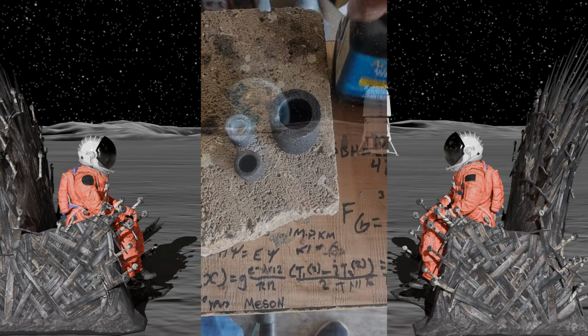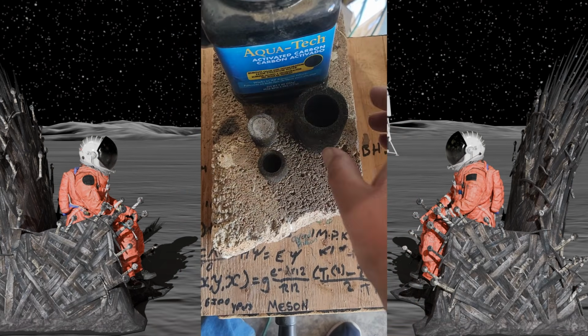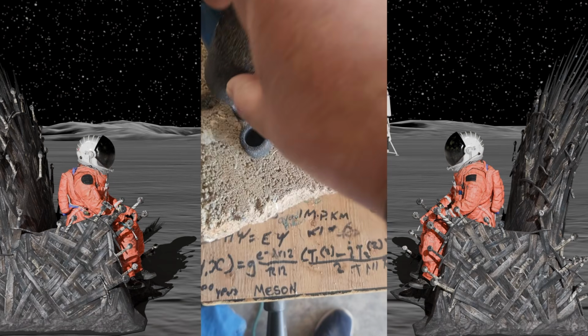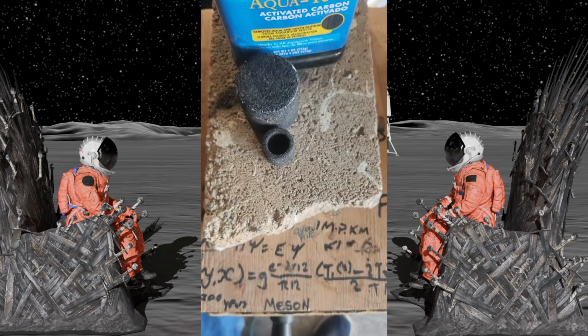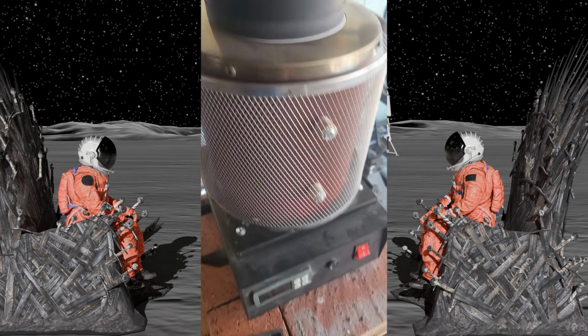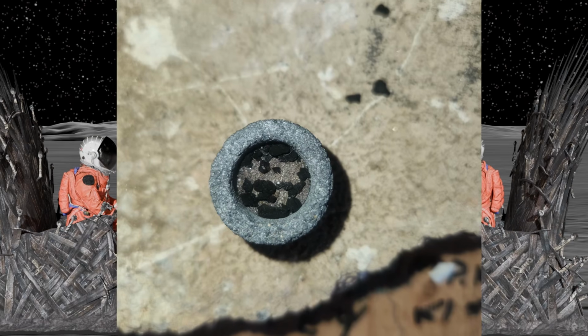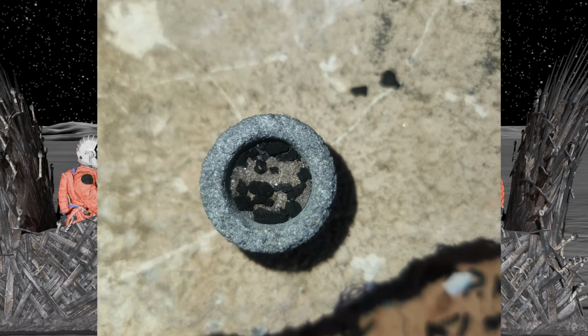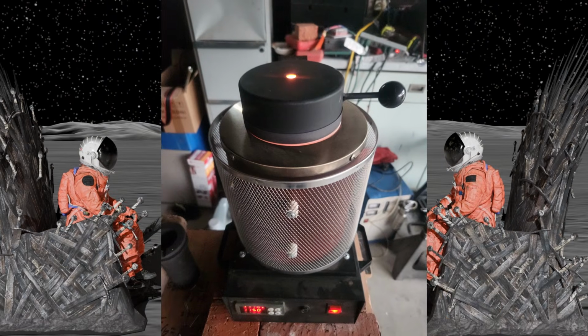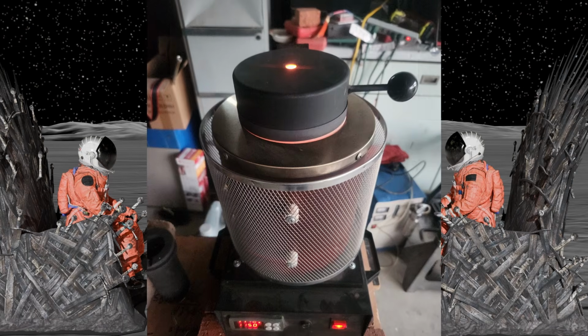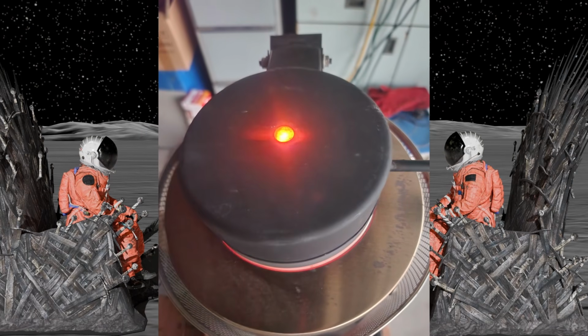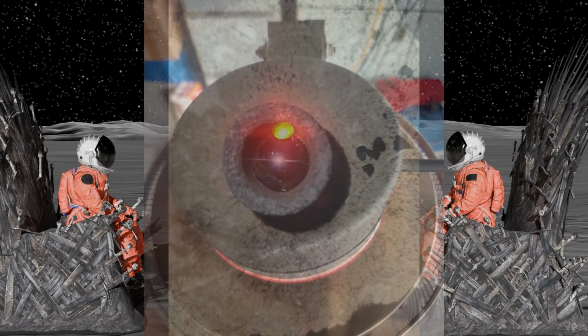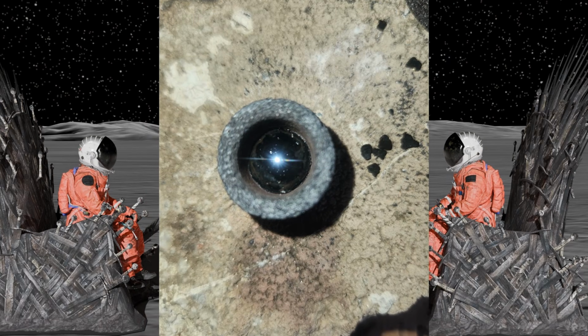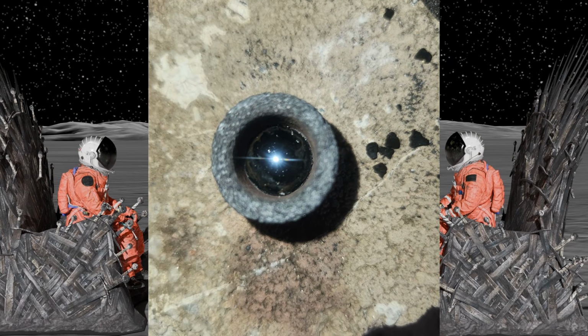So the first refining experiment we did was carbothermal reduction, not because carbon is common on the moon, but because it's sort of the industrial standard for bulk reduction, namely for iron oxide in the steel industry. And for that reason, despite the fact there isn't much carbon on the moon, we still did this to get a strong benchmark, which we could compare to the other more experimental reduction methods done later. And the results were, well, unsurprisingly good, right?